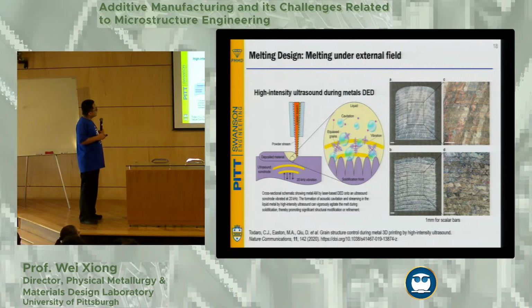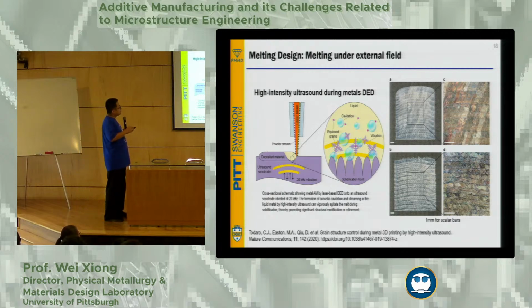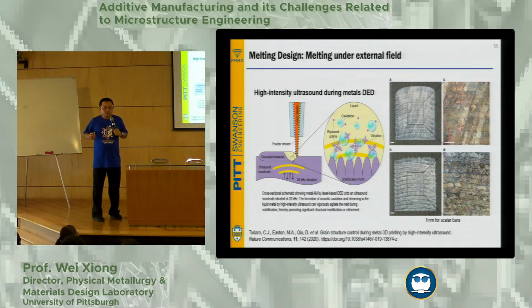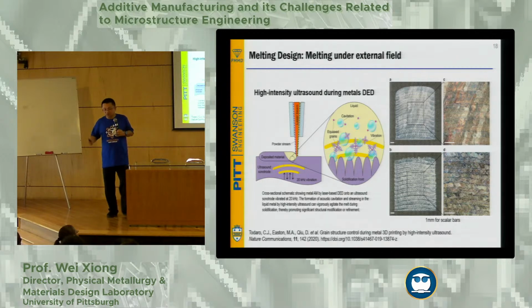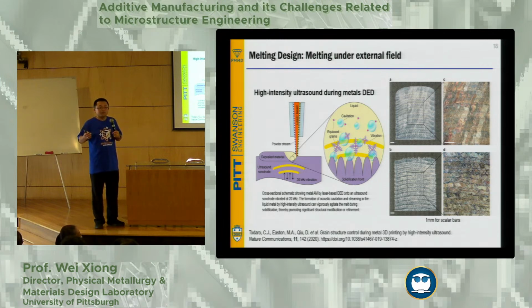As you can see, people are actually not only using the melting process from the heat source, but also using some ultrasound to control the melt pool. Therefore, you have actually vibration happens during the melting. Through this, you can actually refine the grain structure as a received one, and you can see this is actually much refined if you think about the comparison with the typical one that you do without extra field with ultrasound. All right, so this is one possibility that you can use, and actually some of the people also considering using magnetic field. That's actually also typical once you do a conventional melting with arc melt.